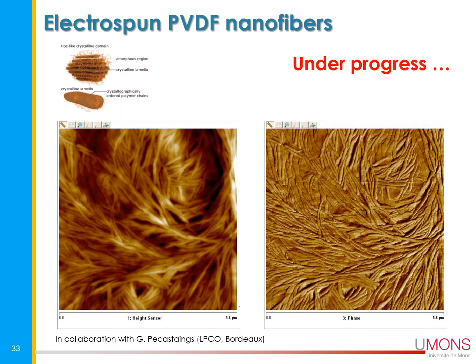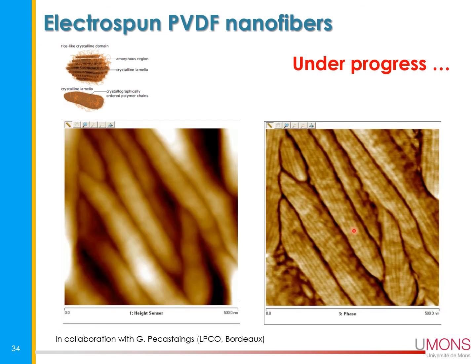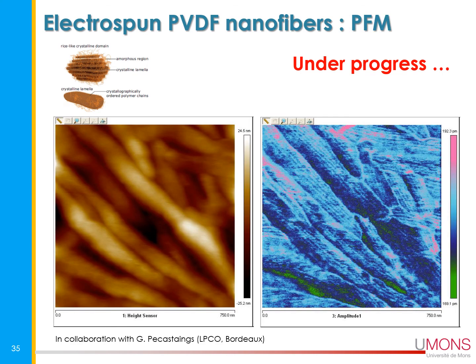So what we did, and this is now in collaboration with the people in Bordeaux, this is some PVDF nanofibers. You can see here a 5x5 micrometer scan size. This is the phase. If you zoom, you can see once again those lines, and those lines are most probably, as we saw before for the work of Johan Hafner, about the crystalline phase in those fibers. And we started to make some PFM.